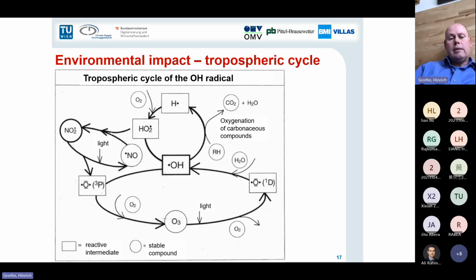The NO2 reacts with the light and is cleaved, and so you have nitrogen monoxide and oxygen atoms in a ground state. The oxygen atom then reacts with molecular oxygen, forming ozone. The ozone reacts with light, forming oxygen atoms in an excited electronic state. And this oxygen then reacts with water, with humidity, and forms OH radicals. And the OH radicals are a very important substance. They are considered like the soap, the washing powder of the atmosphere, because the OH radicals attack all kinds of organic materials. And so the OH radical can oxidize hydrocarbons to carbon dioxide and water, abstracting hydrogen atoms. And these hydrogen atoms then in turn can react with molecular oxygen, producing HO2 radicals.